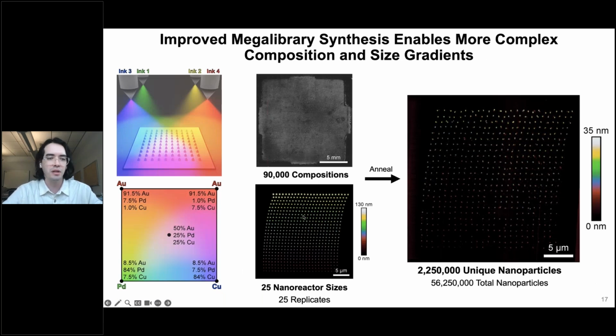And so with this method, we can really push the limits of our composition and size control, where in this case, we're using that spray application technique on the pens, but we can do now 4 different sprays. And so we can spray any mixture of elements. In this bottom left example, we're spraying gold at the top 2 corners and then palladium and copper at the bottom 2 corners. And we can predict the design space that we're working with. So going up for like 91% gold, 7.5% palladium, 1% copper, for example, and having every composition in between those, that design space. And so essentially, each pen tip is now coated with a unique composition. We have now 90,000 total compositions that we're patterning.